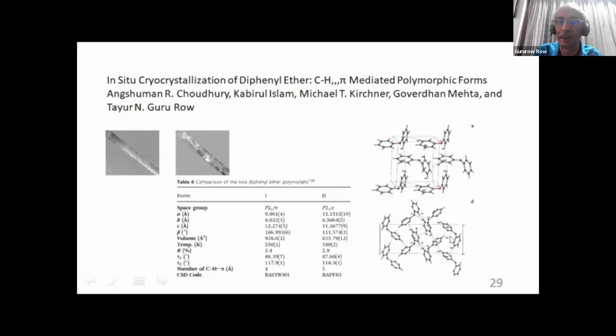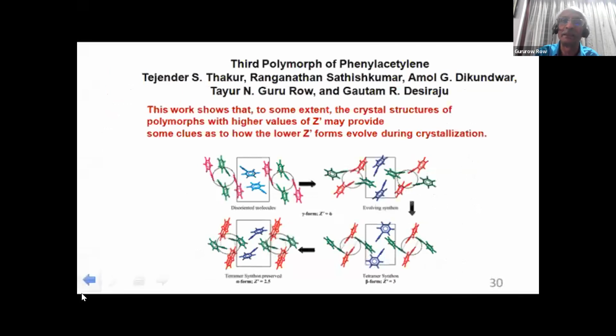And the two packing motifs are essentially changing in terms of weak interactions involving CH pi. This is, in fact, the first example of a solvent demonstrated to have polymorphic modifications. The other example is the third polymorph of phenylacetylene, which we looked at, where we essentially see the pathway of crystallization. So this work shows that to some extent, the crystal structures of polymorphs with higher values of the number of molecules, referred to as Z prime, may provide some clues as to how lower Z prime forms